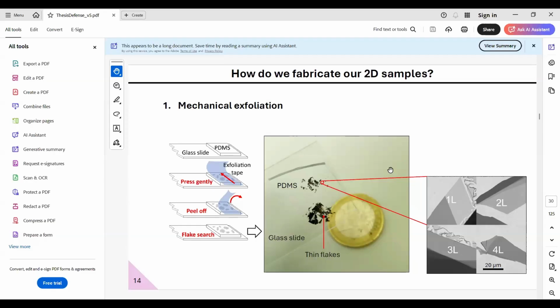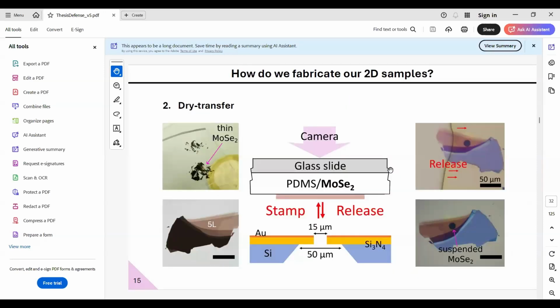So I trust that you did the things. Regarding the adhesion of the flakes, when you use this gold metallization of the silicon nitride membranes, you do that in order to increase the adhesion of the flakes on the membrane, right? So to make your life easy when you're going to transfer over the hole, I understand. Did you notice any difference between using freshly evaporated samples and old gold, let's call it like that? Yes, actually,